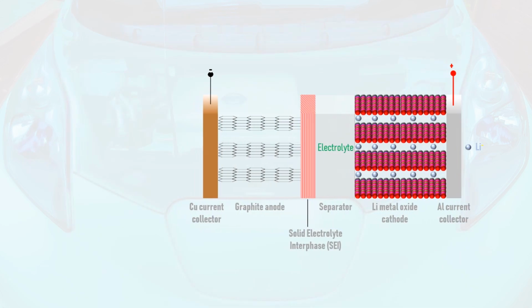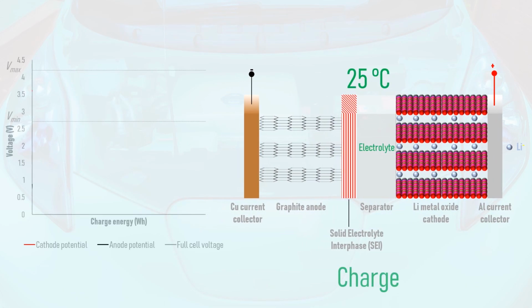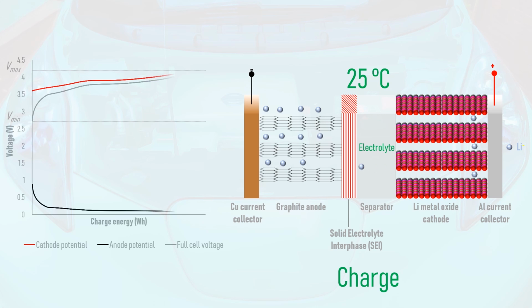When a lithium-ion cell is rapid charged, the cathode voltage increases as it loses lithium, but the anode voltage decreases as it gains lithium. At an optimum charging temperature and current, a conventional graphite anode approaches 0 volts versus lithium as it approaches 100% state of charge, but does not reach 0 volts unless being rapid charged with too high a current or at too low a temperature.